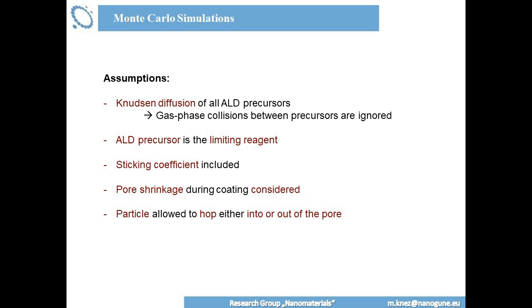If we go to the third model, it's a Monte Carlo simulation, so it's not really a physical derivation in a paper. It's a Monte Carlo simulation, but also regarding the Knudsen diffusion here, the simplified factors are the same as in Gordon's model. The ALD precursor is the limiting reagent. The sticking coefficient is included, so it's a little bit of an improved model.